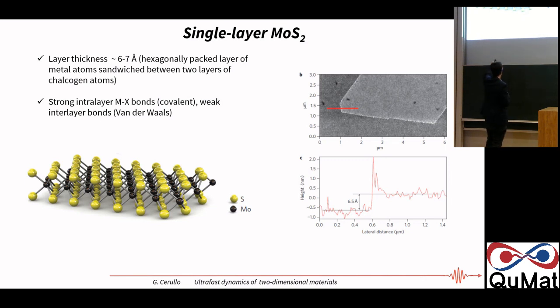You see the molybdenum atoms in the middle and the sulfur atoms at the sides. And here you have strong intralayer covalent bonds. And then each layer is held together with the others by weak van der Waals interaction. So it's not really as thin as graphene, because now you have 3 layers of atoms, but still, here you see in an AFM, a single layer is 6.5 angstrom. So you can call it an atomically thick material.